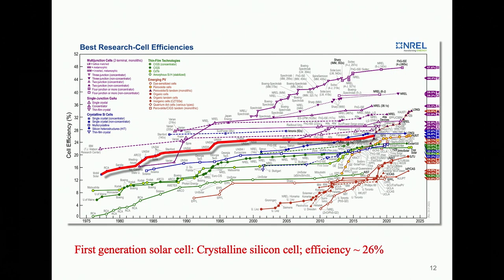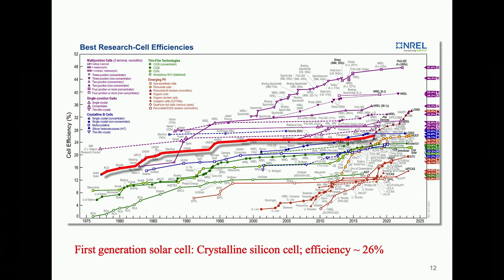Roughly speaking, so far, researchers have worked on three generations of the solar cells. The first generation solar cell is the crystalline silicon cell. Its efficiency increased at a relatively fast rate between the 70s and 90s last century. Then it experienced a stagnation period for almost 30 years. Interestingly enough, the efficiency has started increasing again since 2015 and reached a record high efficiency of about 26% as of today. These crystalline silicon cells have excellent efficiency and also superb endurance, but it is relatively expensive to make, especially in the early stage of its development.